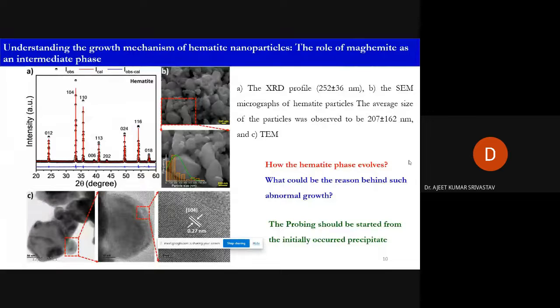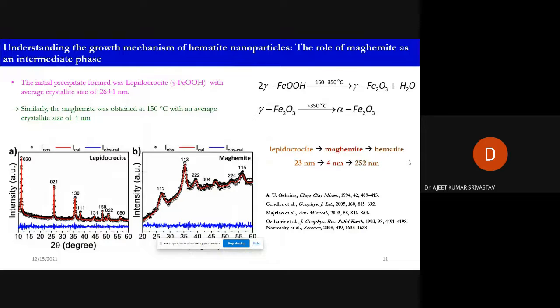Okay. So the first question that comes here is how the hematite phase evolves. What could be the reason behind such abnormal growth that we have observed here? And then the first thing we can start with, to know, is what the initial or precursor phase is which forms during the synthesis. Okay, fine. So that is how we are going to start. So when we investigated the initial precipitate, we found that it is lepidocrocite, gamma FeOOH, with average crystallite size of 26 plus minus 1 nanometer.